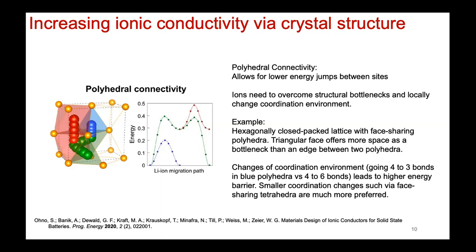Well, there's a concept called polyhedral connectivity, and that tells you if an ion has to move through, let's say, a tetrahedral face going into another tetrahedron, or an octahedral site, in the center of the octahedron, so an 8-sided polyhedron, and then migrates to another octahedron and then into a tetrahedron, that affects what's called the bottlenecks that it has. So here's an example where if it moves through a tetrahedral site, the energy barrier is about 0.2 eV relative to, let's say, going from this blue and then migrating along this green path. So you can actually predict and calculate ab initio.